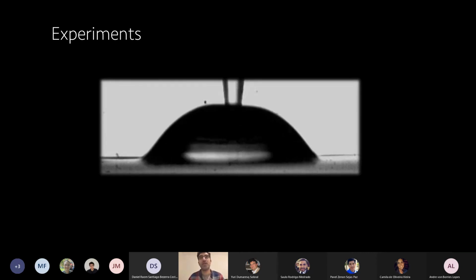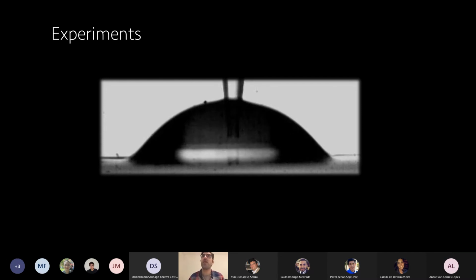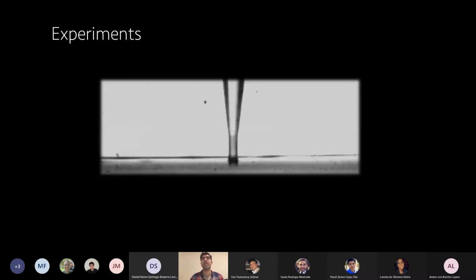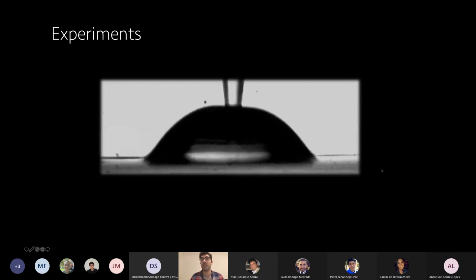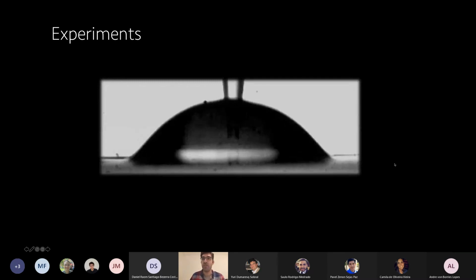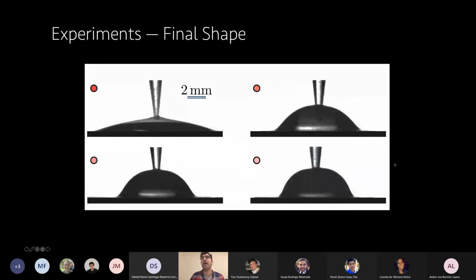We got a nozzle, we deposited a blob of liquid on a surface, we let it relax, we know the volume, and we basically let it spread enough so we reach the final shape, and we look at the final shape. So here are 4 examples from top left to bottom right. I'm increasing the yield stress. So it's not rocket science. As I increase the yield stress, droplets spread less, as you can imagine with a toothpaste experiment.